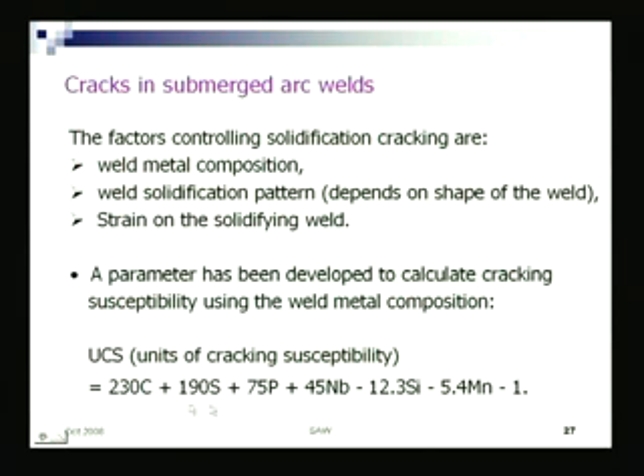So, as you can see that UCS is reducing with increasing silicon and manganese, but increasing heavily with sulfur as well as carbon. That is why high strength low alloy steels have very low carbon percentage, whereas high yielding steels have a higher carbon percentage and are very difficult to weld.